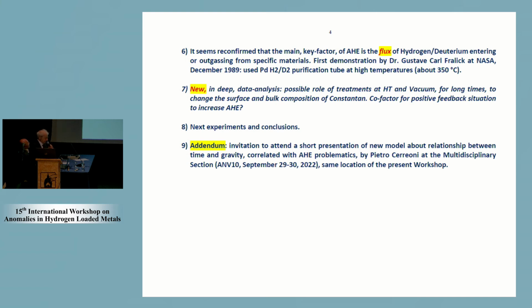Again, we reconfirm that the main parameter, the main effect that promotes the anomalous effect, is the flux of hydrogen or deuterium along the materials. The flux phenomenon was discovered by Professor Fralick at NASA in 1989, the beginning of cold fusion, but unfortunately these data were not made public for several reasons. And another point: in addendum I had one paper of my collaborator about a new model, but it will be presented in the Italian version of this conference 2 days later.